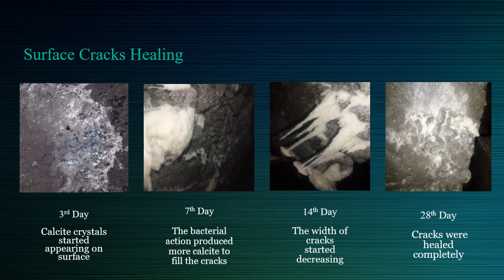The crack widths are measured at different points and marked for observations of self-healing. As we can see, on the third day, calcite crystals started appearing on the surfaces, and on the seventh day, the bacterial action produced more calcite to fill the cracks. On the 14th day, the width of the crack started decreasing, and on the 28th day, the cracks were healed completely. The widths are measured, and the difference between the original crack width and that observed on later days was considered as a measure of self-healing.